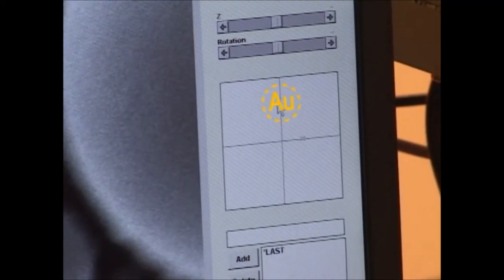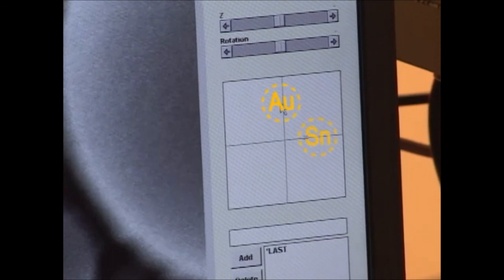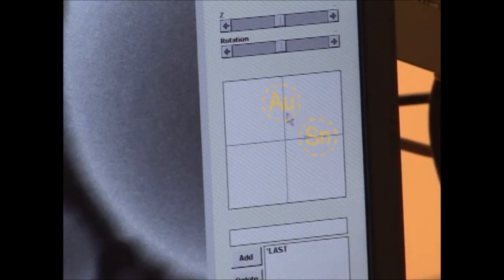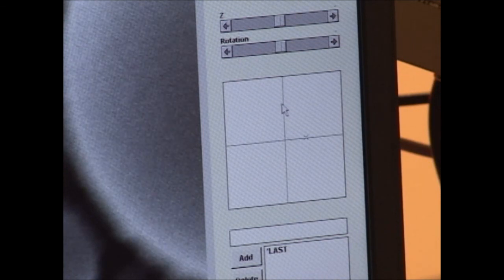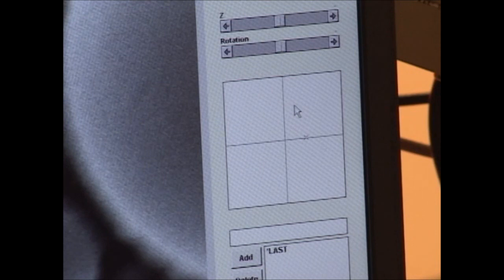Gold nanoparticles at 12 o'clock, and I put this tin sample at 3 o'clock. And those clock positions I was referring to are from this stage table. So when you put the sample holder into the chamber, samples that are facing away from you are at 12 o'clock. They'll be along the positive y-axis here. And the 3 o'clock position is the positive x-axis here. So I can either make a mental note of where those are located, or I can draw myself a map before I close the chamber door so that I know where things are going to be on this table.